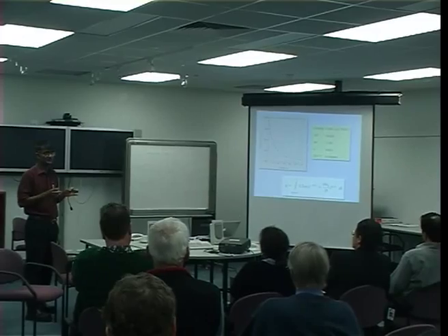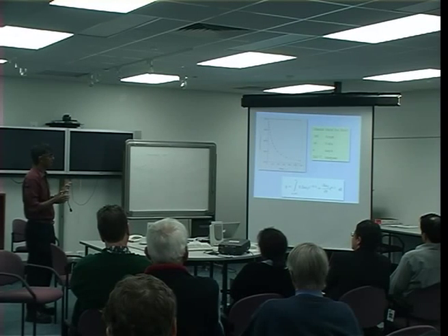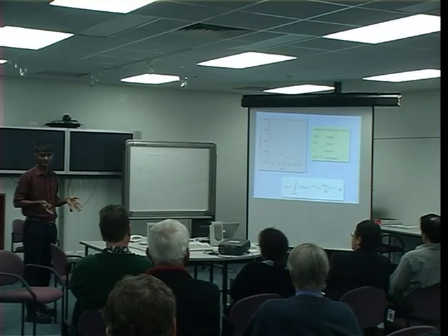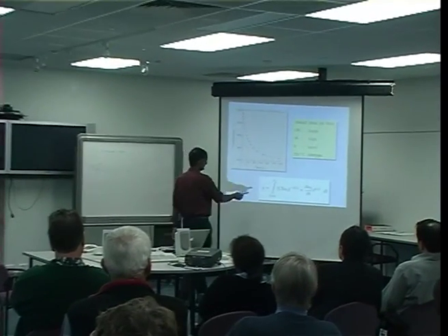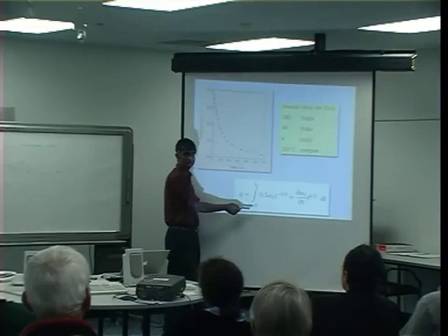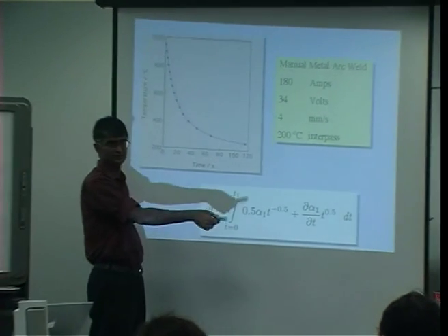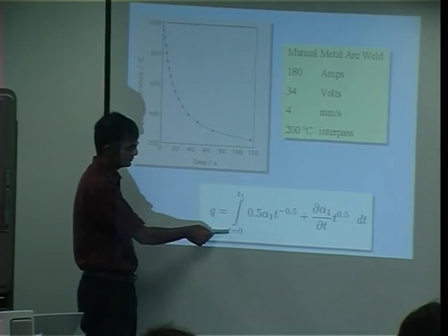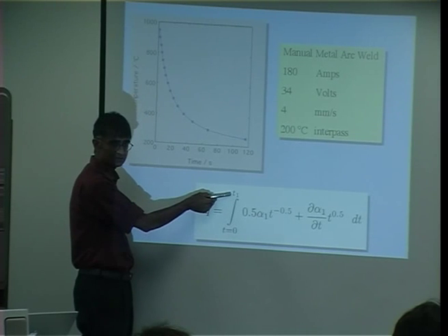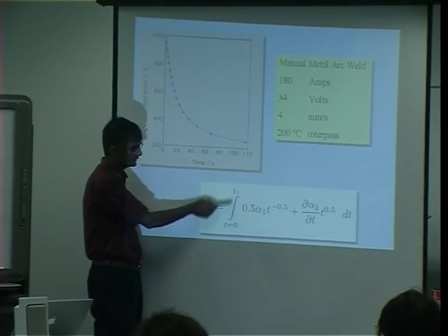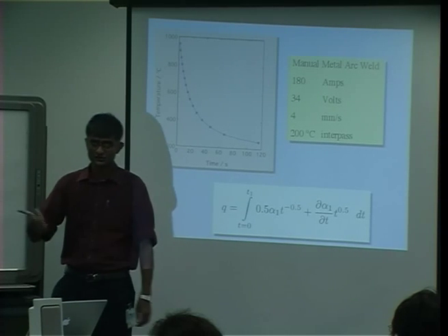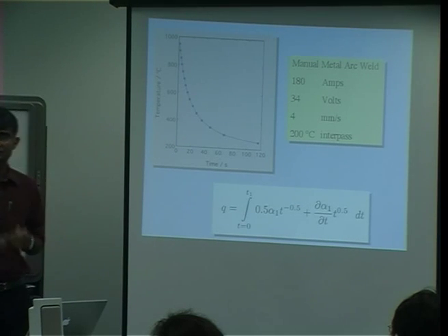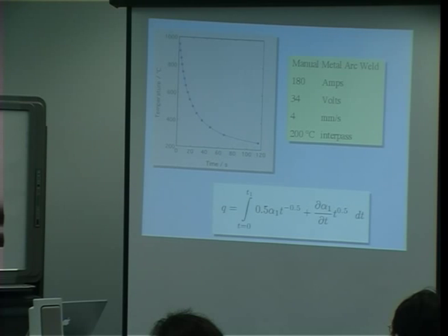So if you use a laser method, you simply have to modify that curve to take account of the cooling conditions. And then you integrate the growth kinetics over a temperature range instead of doing it at a constant temperature, where this is the point where the transformation initiates and finishes. And where do we get this information from, where the transformation begins and finishes? Well, we have to be able to calculate a time temperature transformation diagram.